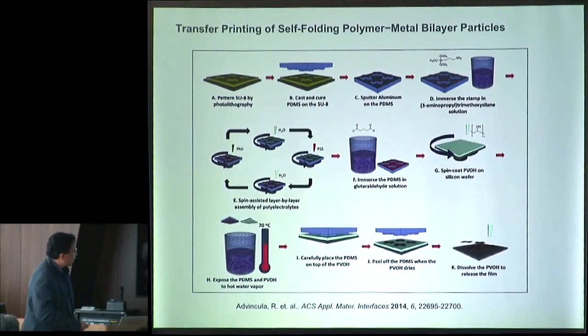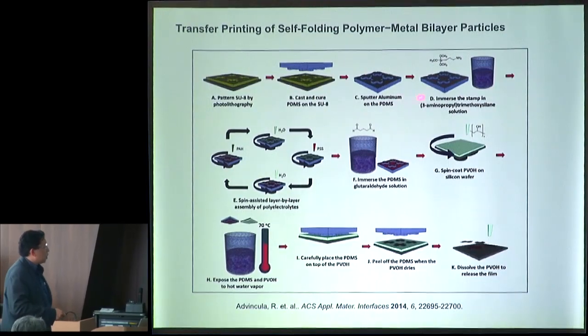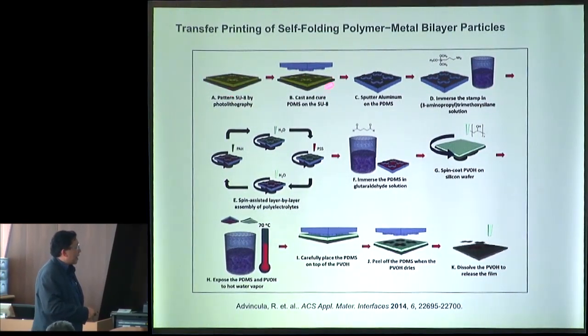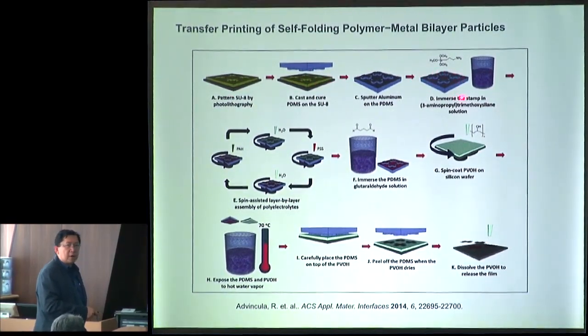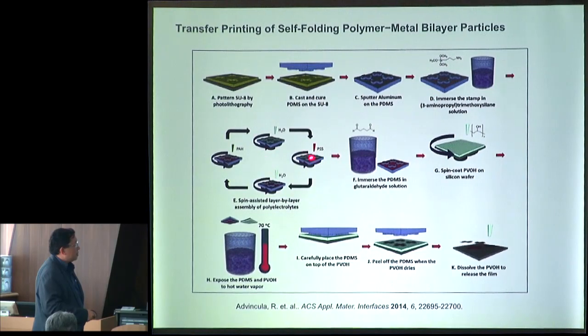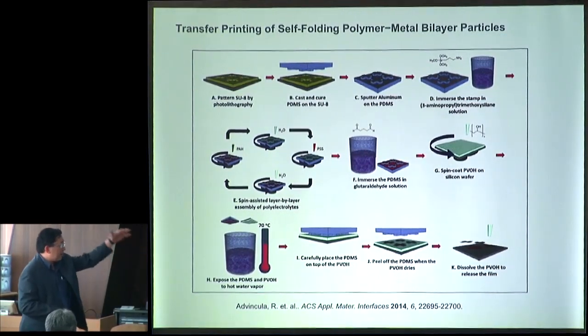To do that, we embarked on this procedure where we made a pattern by lithography or reactive ion etching, and then we took this pattern and added layer by layer of polyelectrolyte, and then we evaporated aluminum on top of it. Now, evaporating aluminum gives us the hard layer.